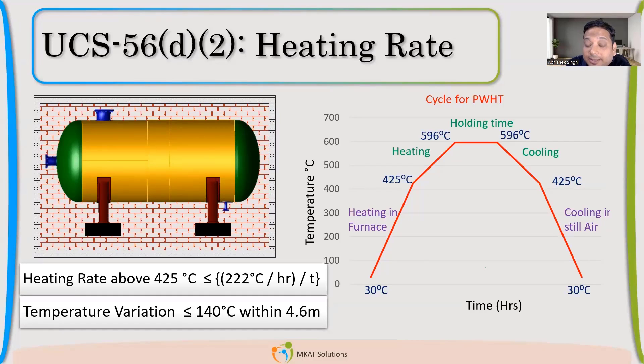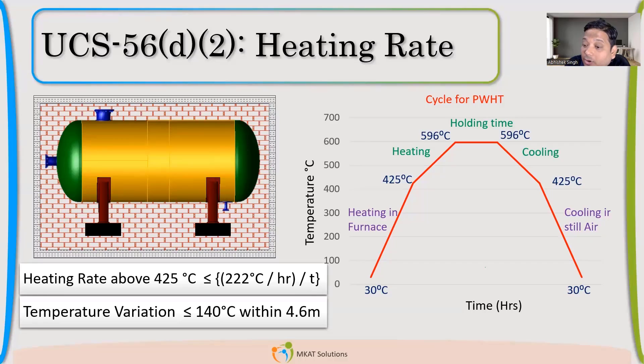The second point: once the job is in the furnace, the temperature between any two points that are 4.6 meters apart should not vary by more than 140 degrees Celsius. To verify this, we need to maintain lots of thermocouples. Thermocouple positioning should be based on this 4.6-meter value — you need a thermocouple located at every 4.6 meters so that you can confirm the temperature is not being violated.